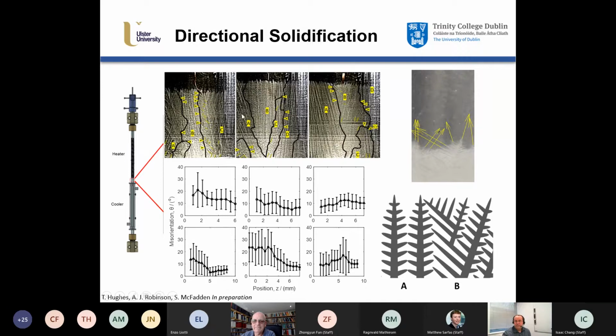And also looking at another automatic system that tracks the front, but then it crops a window around the front position, and then it concatenates the figures and builds up this true representation of the growth. And what you can see is a lot more detail. So you can see the orientation, the colonies of the grains, the grain boundaries, and you can see primary and secondary dendrite arms. So we did quite a few of these experiments, and we looked at the orientations, and you'll